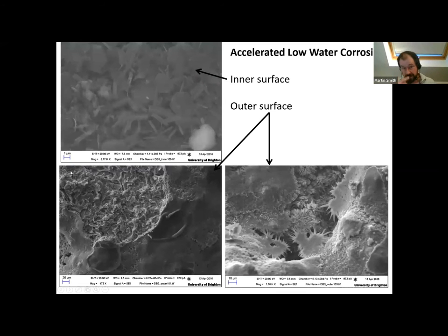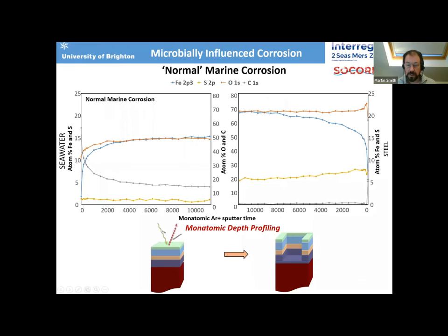So this is the end product of a sample viewed after we've done an XPS depth profile into it. We can see the crystal structure of the sulfate minerals. On the outer surface, you can see biofilm developed. And at the edge of the ablation crater here, you can see where that argon beam has cut across minerals within the corrosion structure. So that gives us the elemental composition with depth into one of these corrosion samples.